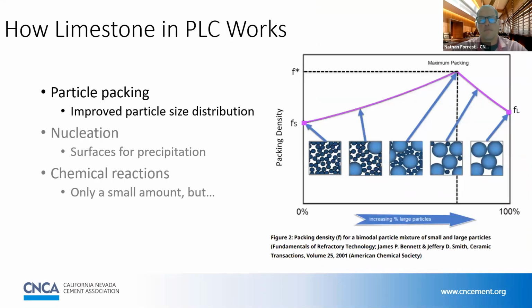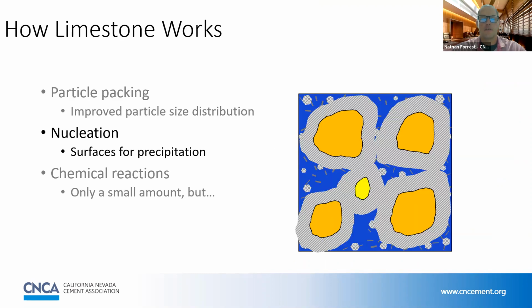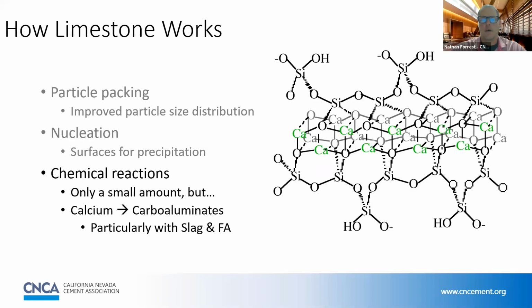A few different ways that Portland limestone cement works. The first is by improved particle packing and density. We do this in our aggregates for concrete or road base or anything else that uses aggregates to optimize the void structure and maximize the density. And the same thing happens here with our cementitious package in our concrete. It also creates additional nucleation sites from which our chemical reactions in our concrete can emanate. And the third way is through chemical activity. These are somewhat limited, but can produce noticeable strength results when used in the presence of aluminate containing supplementary cementitious materials like slag and fly ash.